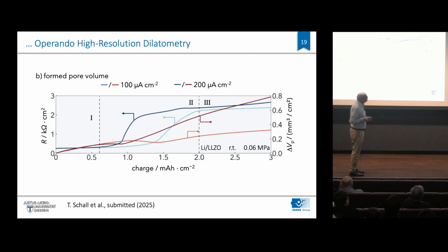And what you see here is an experiment in this busy slide. Again, this is the charge we take out of the lithium metal, and this is the pore volume that is being created. You see here the red curves are with 2 different charge current densities. In fact, from the very beginning we create pore volume. And that means that you can't avoid, and this is really a zero pressure experiment, only essentially 0.6 bar pressure, from the very beginning, pores being created in the lithium, which of course is a critical issue.